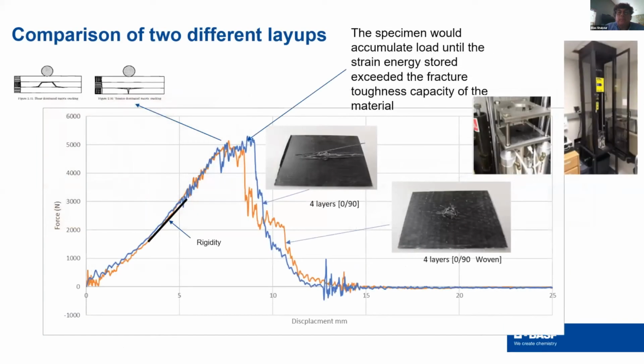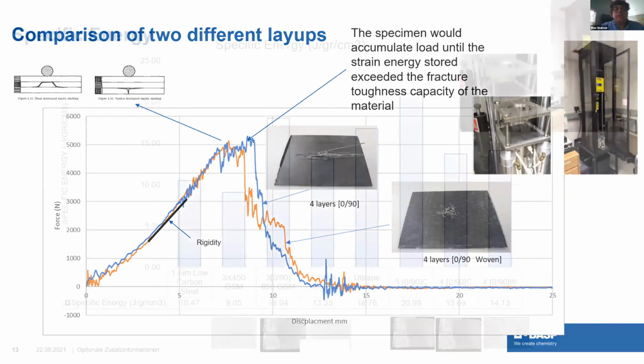And we went beyond. So what I showed you is semi-structural. We went beyond and we did an investigation for high impact. And that's where we use continuous fiber. So this application can work on continuous fiber. As you can see here, this is a high impact of 130 joule impactor with 4 layers of 0-90 continuous and woven. And you can see the difference of the fracture, but yet it has almost the same energy absorption.